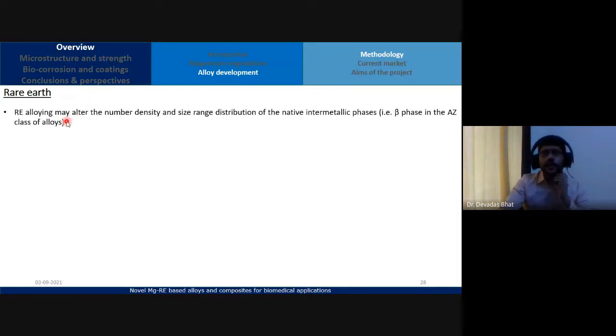So rare earth alloying, it will alter the number density and the size range distribution of the native intermetallic phases. Okay, it could be the beta phase in the AZ class of alloys. So it will modify the distribution with respect to the number density of such phases.